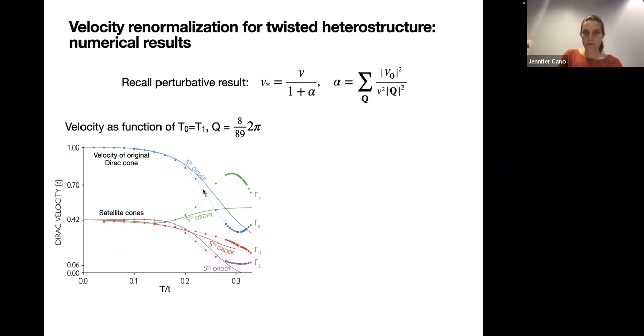And you can see that we capture this general trend, which is as the potential is getting bigger, this velocity is getting smaller, and eventually it starts to nosedive. Then the perturbation theory keeps going, but numerically there's some minimum and it starts coming up. This is rather neat because we've achieved a pretty significant renormalization of the Dirac cone velocity, down to around, say, 0.3 or 0.4 of its original value. And these other plots are showing those satellite cones. We can also track their velocities, but we're not going to do anything with those for today. So the main point is that our numerical results back up our perturbation theory,